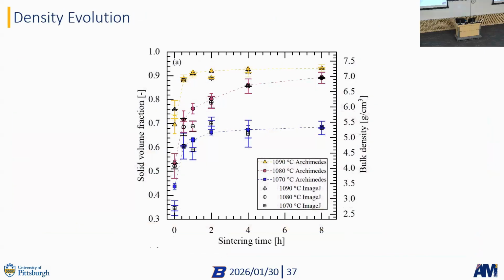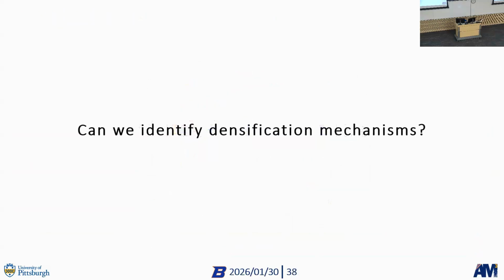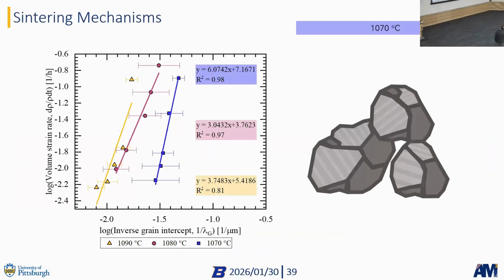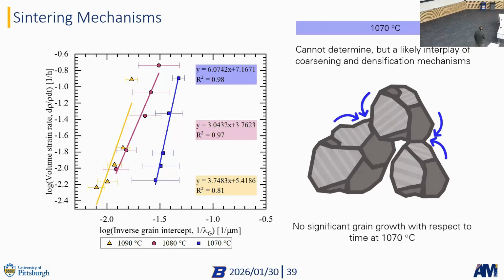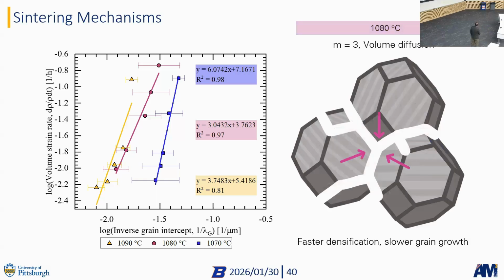Here you can see we reached around 95% density for these materials. We use this graph, which shows the density of these materials for different sintering temperatures and times, to again identify densification mechanisms. So when we go to 1070, which is this line here, the slope in this volume rate versus inverse grain intercept gives you an indication of the densification mechanism. For 1070, the lowest temperature, it's again very difficult to identify. Probably we have an interplay of coarsening and densification mechanisms, and we also have a lot of defects that haven't been repaired at this temperature. For 1080, we do see volume diffusion.